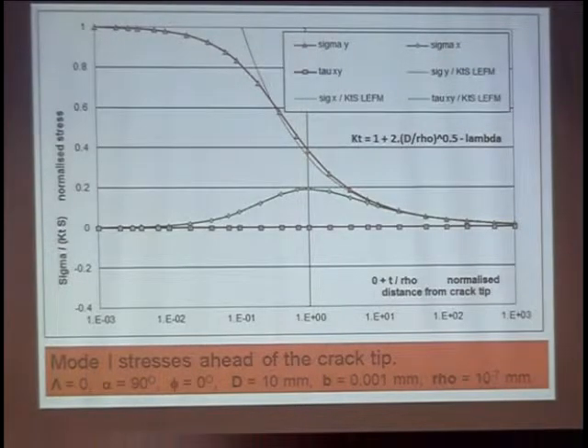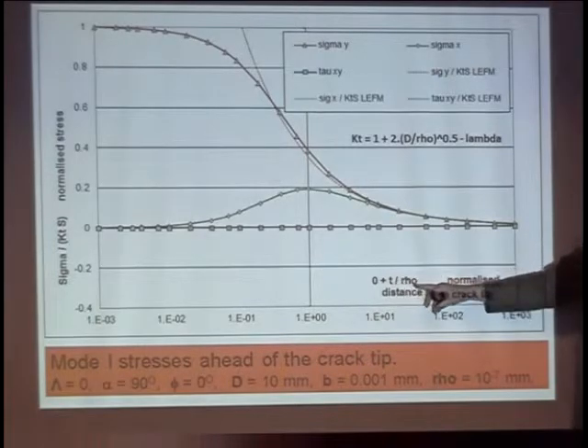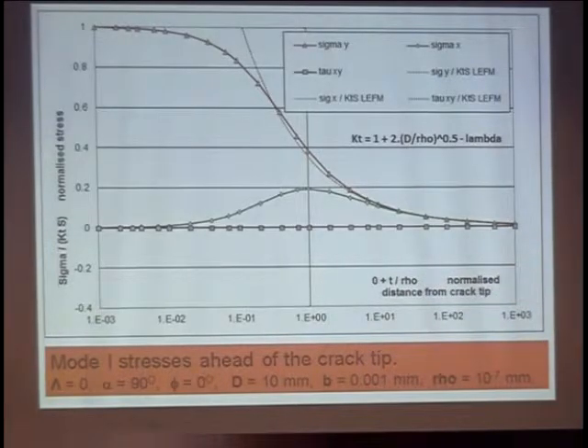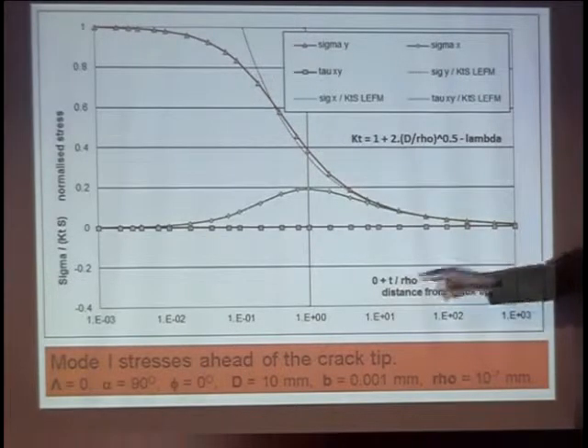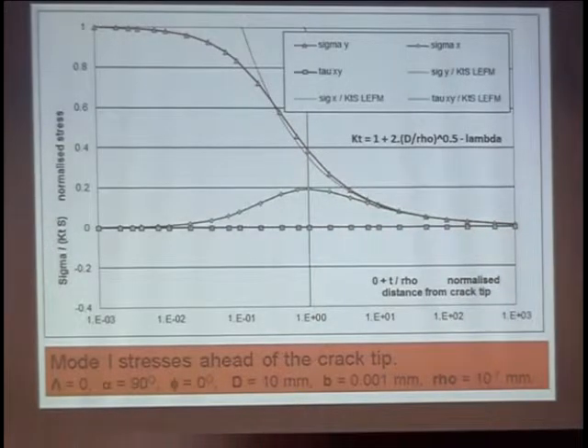All the graphs that follow look like this. In terms of the axes, they're normalized axes. Logarithmic scale horizontally, which is distance from the crack tip divided by the radius of curvature, rho. So r over rho is just normalized, and when it's 1, of course, that's saying just 1 radius of curvature away from the crack tip. So that's really quite close to the crack tip there.